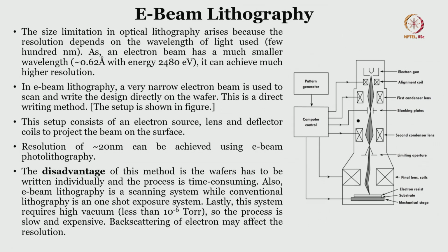Electron beam lithography overcomes the size limitation of optical lithography, because the resolution depends on the wavelength of the light used, which is in the range of a few hundred nanometers, while the electron beam has a much smaller wavelength, close to 0.62 angstrom, with energy of 2480 electron volts. So, it can achieve much higher resolution.